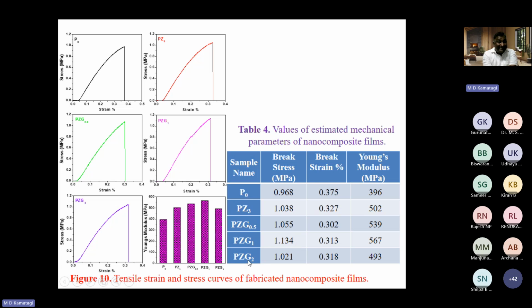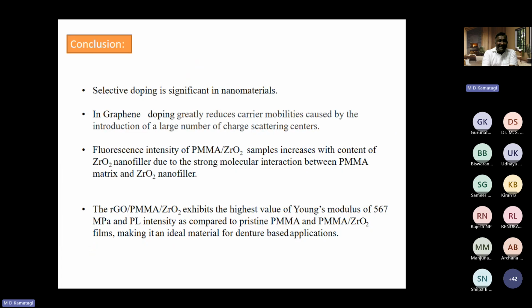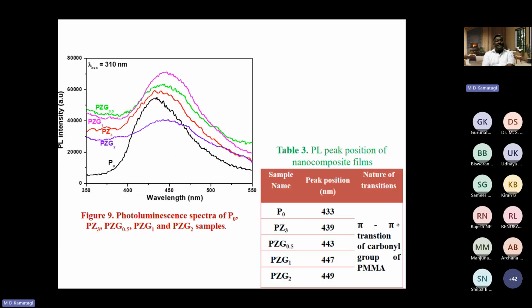But whereas this higher concentration reduced graphene oxide shows the lower mechanical strength. So doping, though it increases the mechanical properties as well as the optical properties, the dopant selection becomes very important.